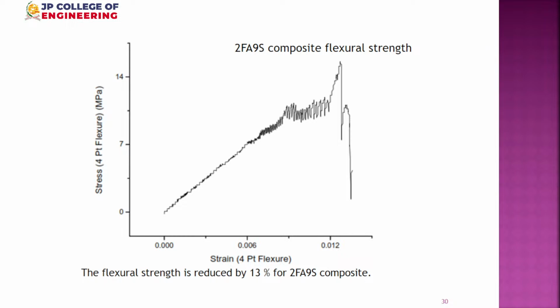So the particles also participate in the load distribution. The failure occurs again, but another particle offers resistance. Therefore, the load builds up. There is a fracture again, at a particle-resin interface. Load falls, but again another particle raises its resistance to the load. Like that, many serrations, the drop and pickup. This is what we call the serrations. This clearly shows that our particles participate in the load sharing. Finally it goes to a peak value and then failure occurs.